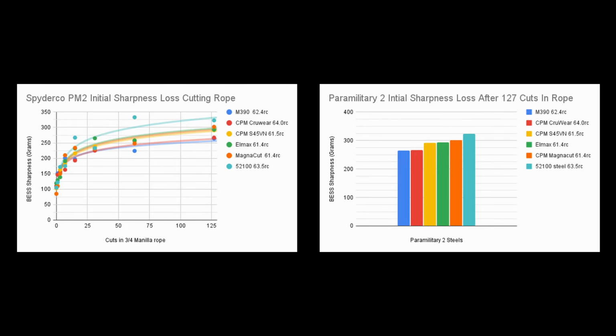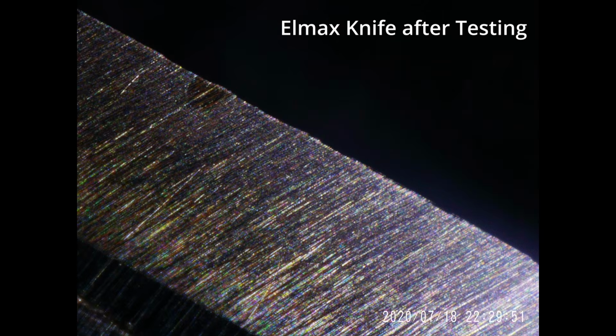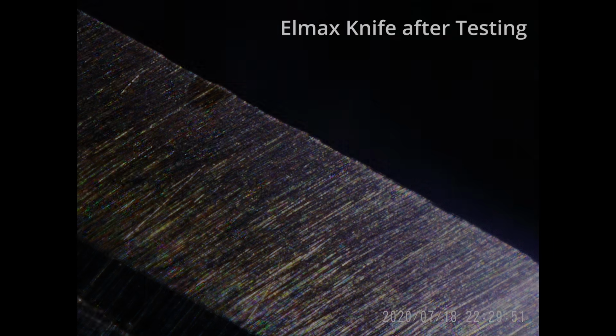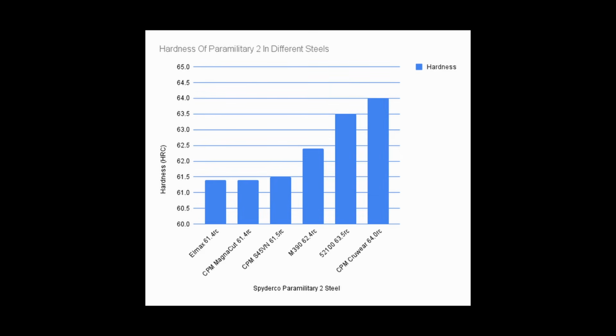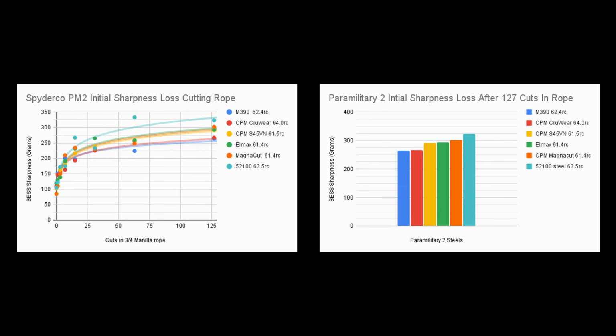Sean told me that he was surprised by how much force was required to cut through the rope, especially at later stages of the test, and looking at the edges under magnification revealed deformation in the edges. The hardest knives were in CPM Cruwear at 64 Rockwell C and 52100 at 63.5 RC, and they showed the least deformation as expected. However, edge wear was also seen at the edges, most visibly apparent in the 52100 knife, as that steel has by far the lowest wear resistance in this comparison, and so still saw the worst sharpness of any knife at the end of the test.